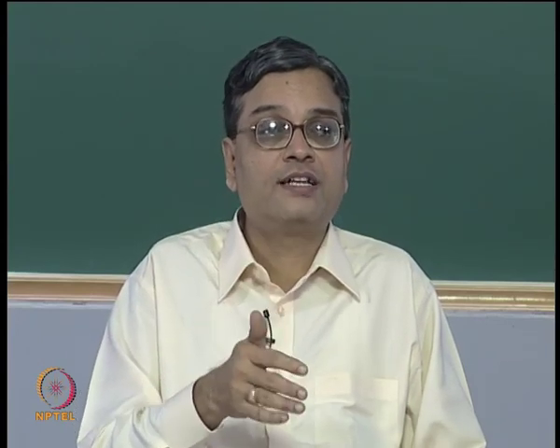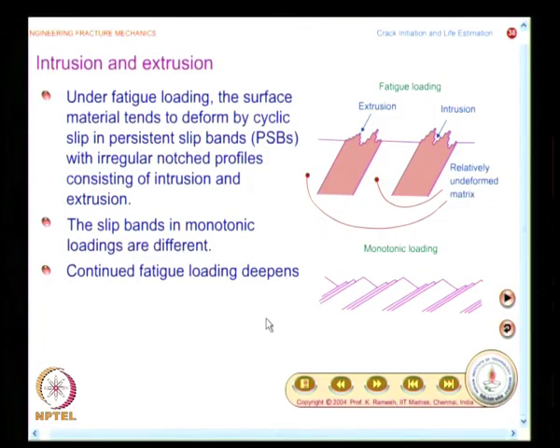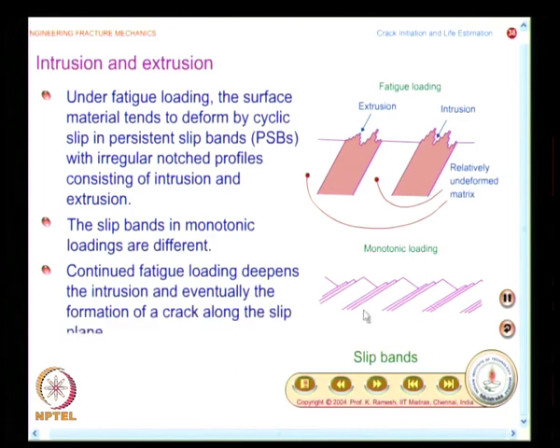you will have easy formation of surface cracks and fatigue life also would be less. And what this slide shows is, as the number of cycles increases, you will have extrusion and intrusion form. That is what it says, continued fatigue loading deepens the intrusion and eventually the formation of a crack along the slip plane. So, what you have here is the slip planes come out of it, you call them extrusion, they go into it, you call that intrusion, and they grow as the number of cycles are increased.